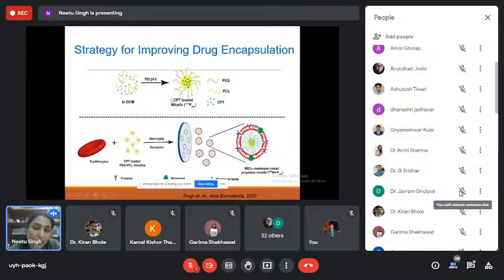So what we did was we had a micelle. We thought of making a polymeric micelle in which this drug will be encapsulated, and this will then get encapsulated inside the nanoerythrosomes. Okay, so this is what we did. So we have the erythrocytes, we have the loaded micelles with the drug, and then it will be hemolyzed and extruded, and you end up with something like this. You have a nanoparticle with the micelle.